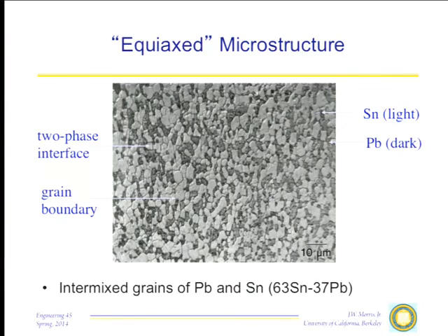And with an all-tin structure, it's much more difficult. With the simple solder, you really just solidify the stuff. If you have almost pure tin, it's very, very difficult to get that in a fine-grained microstructure, which for mechanical reasons you'd really like to have. So in fact, there's an international effort at the moment: how can we refine the grain size of lead-free, tin-rich solders in these very, very fine contacts?